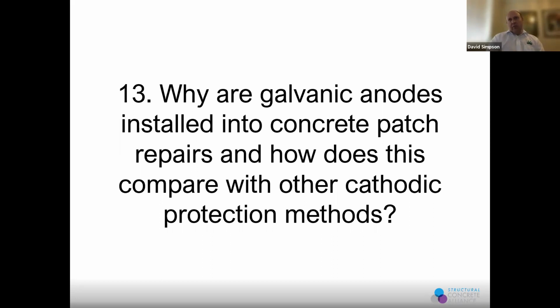And basically with time, people realized it was something we now call incipient anode formation or ring anode formation, depending on where you are. This occurs because when we do a repair, we're taking out where the corrosion was occurring. But realistically, that patch was actually protecting the rest of the steel around it. We've come along, taken it out, cleaned up the steel, removed chloride,